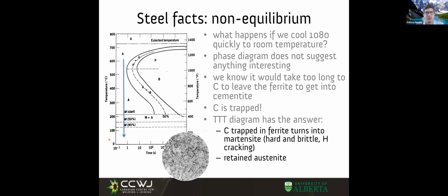The carbon doesn't want to be in the ferrite - we already discussed there's no room for carbon in the ferrite. The carbon wants to go to the austenite, but it needs time to get out of the ferrite and into the austenite because of diffusion. We already discussed that, and we said if we have shorter times or lower temperatures, we need shorter distances. But what if I cool so fast that there's no chance?